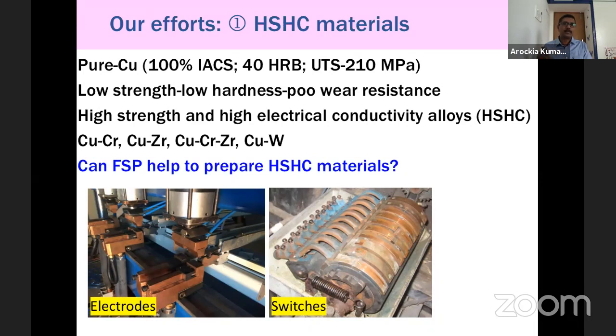So 100% IACS. The pure copper has only 40 HRB hardness, and the tensile strength is only around 210 megapascal. But in the applications I have shown at the bottom of the slide, like electrodes or switches, use of pure copper is not recommended because of its very poor mechanical properties. So in such cases, I need to improve the strength as well as the conductivity.